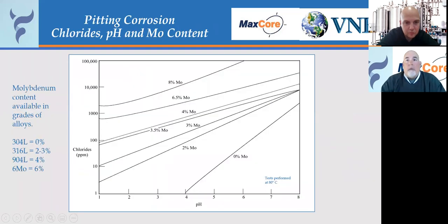So when you're talking about materials, one of the things that gives you corrosion resistance is the molybdenum content a material has in it. If you look at the ASTM standards, 304 stainless steel by definition has no molybdenum content at all. 316 has 2 to 3% molybdenum content, 904L has 4% molybdenum content, and 6 moly alloys have 6% molybdenum content.